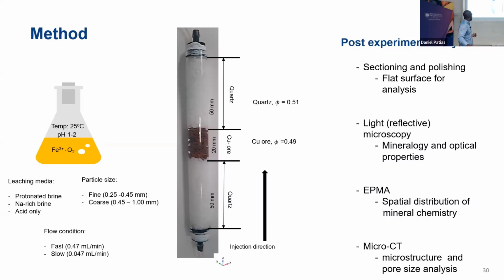So particle size, we did fine and coarse. When I say fine, in my case, it's not microns, it's still millimeter size. And then we tested it for leaching media. And then we did 2 instances of flow rate, so we wanted to see what's the influence of high flow rate and low flow rate on your copper amount.